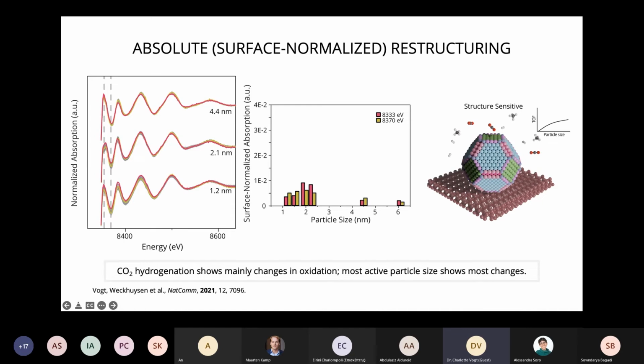And there we saw that actually the surface normalized absorption changes. So for different nanoparticle sizes, of course, you have different amounts of surface, but this is normalized for that. You see that the medium nanoparticle size restructures the most. We see actually, in fact, that our surface restructuring is correlated to the activity of that reaction. So CO2 hydrogenation had this nice maximum at about 2-3 nanometers, and that's also where we see the most restructuring.